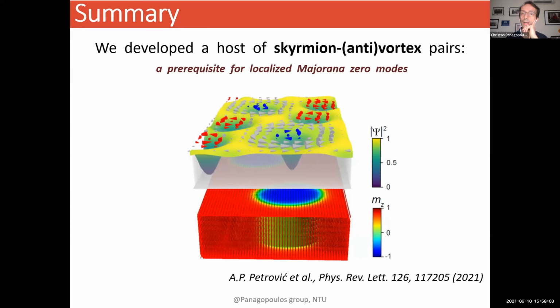Right. So at this stage, we have only looked at the dynamics of the superconducting anti-vortices and vortices. And as I mentioned earlier, they are significantly enhanced, in kilometers per second, one of the fastest ever, actually. We haven't looked at the skyrmions, but indeed, what we do see, however, is that the skyrmion motion is affected, but we haven't looked at that. So this is yet to be done.